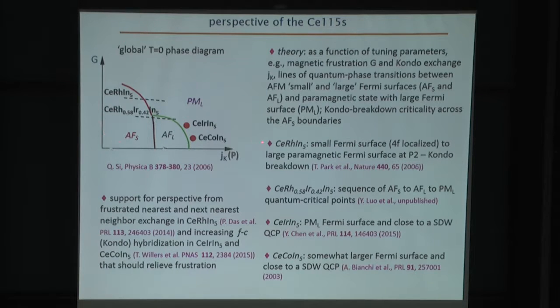So by varying these two tuning parameters at zero temperature, Si and co-workers map out this global phase diagram that includes, again now at T equals 0, the separation of an antiferromagnetic state with a small Fermi surface from an antiferromagnetic state with a large Fermi surface from a paramagnetic state with a large Fermi surface. And this line that separates any boundary from a small Fermi surface to a large Fermi surface involves the critical breakdown of the Kondo effect.